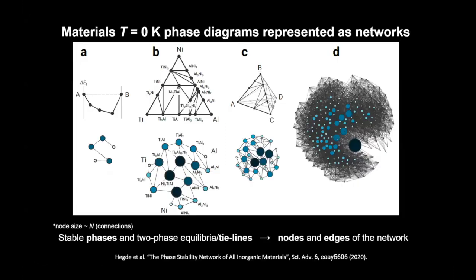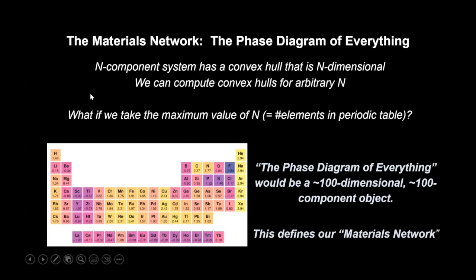So this is the idea. We're going to use these convex hulls, and we're going to map them onto graph representations that tell us something about the connection between various phases in terms of stability. Okay? Now, the interesting thing about these convex hulls is that you can compute them from large databases like OQMD, not just for binary or ternary systems, but for quaternary and higher order systems. This over here on the right is actually a graph representation of, I think, an 11 component convex hull, essentially all of the 3D transition metals plus oxygen. And you can see that the convex hull starts to get very complicated, right? But the nodes of the convex hull are still the stable compounds on the hull, and the connections, or the edges of the network, represent the stable two-phase equilibrium. Okay, so there are two important points here that I need to make about this.